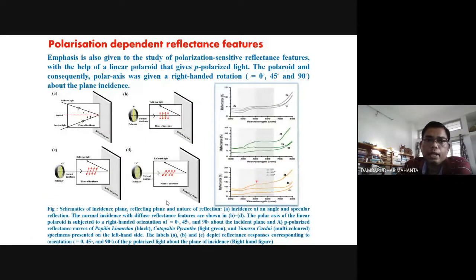We did polarization dependent reflectance features for these samples, and we found that in different regions they are distinctly different. For example, in the UV region, in the first case, in the black case, you could see for 0 degree polarization, 45 and 90 degree, S plane, P plane, and in between S and P, while between 500 and 650, they are very, very close.